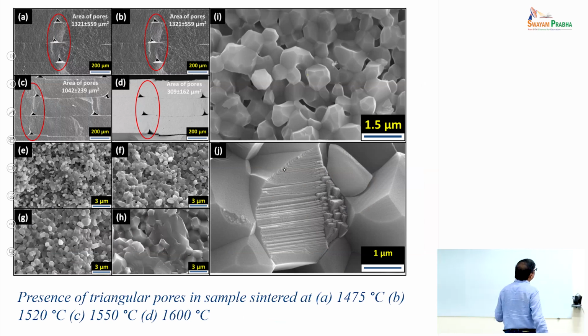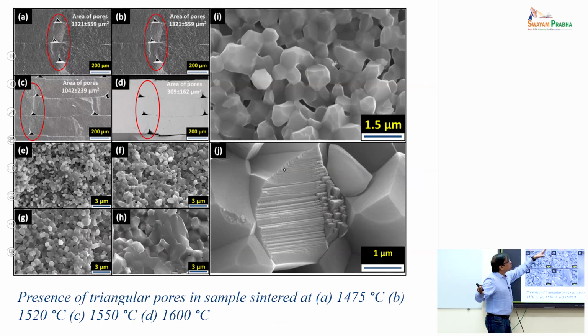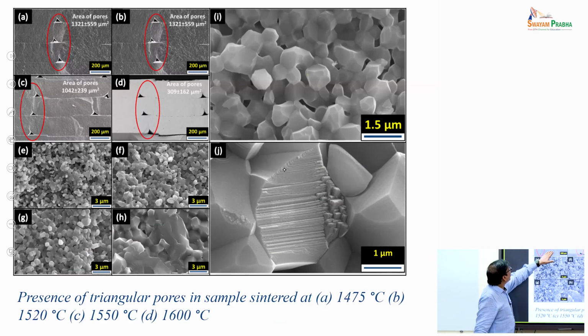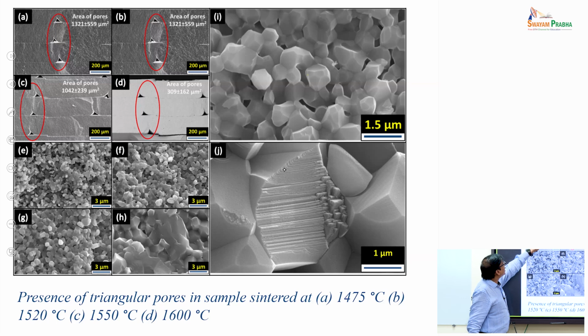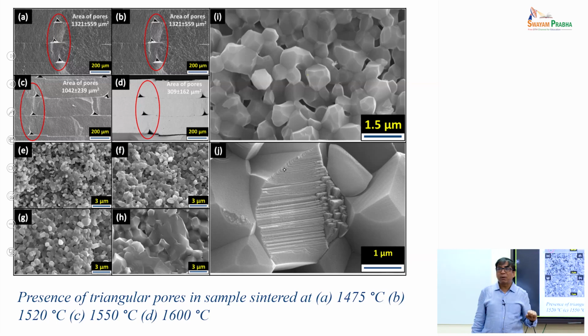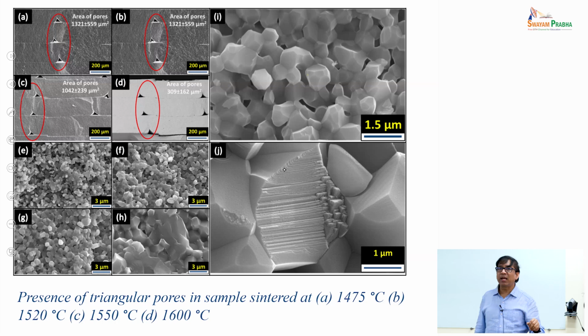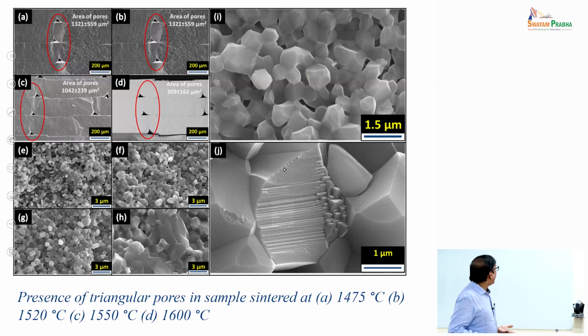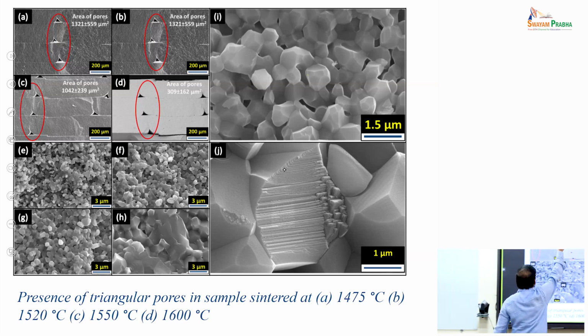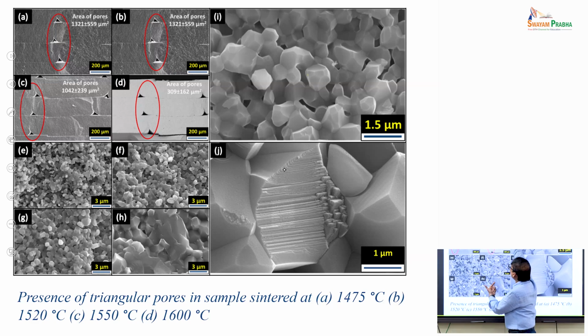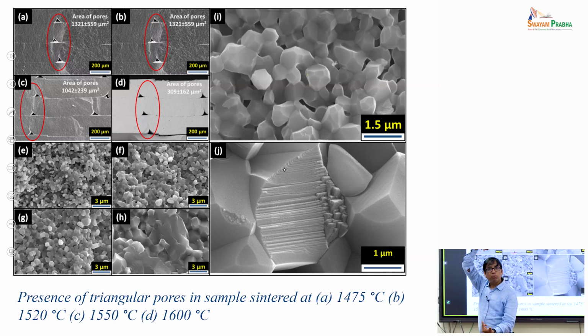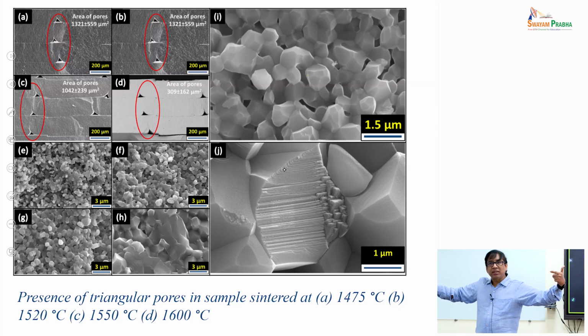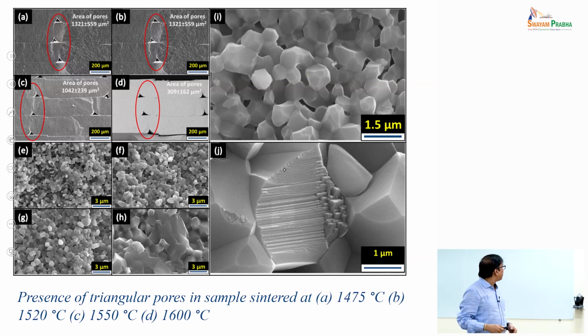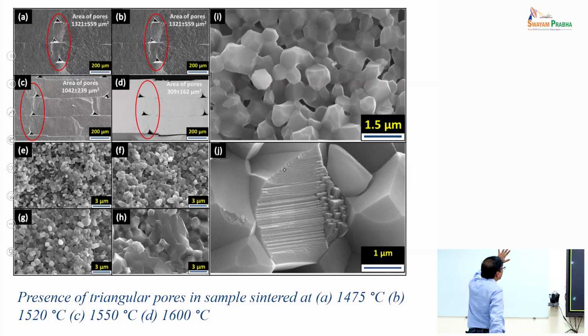This is something that I think anybody who has worked in fused filament fabrication would recognize. You can see these interlayer weak points, including these open spaces that we see in fused filament based ceramic components. These are actually weak points for ceramics, and therefore when we do mechanical testing, we wanted to test both in the printing direction as well as in the direction perpendicular to the printing direction. I'm just showing you the microstructure, how it looks.